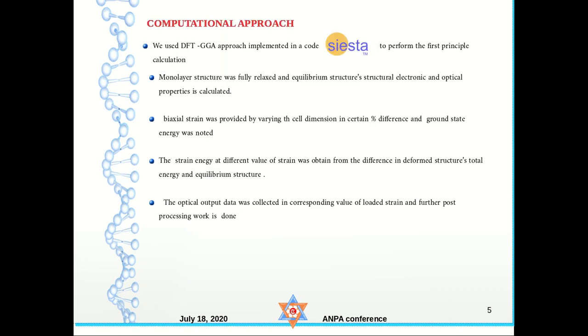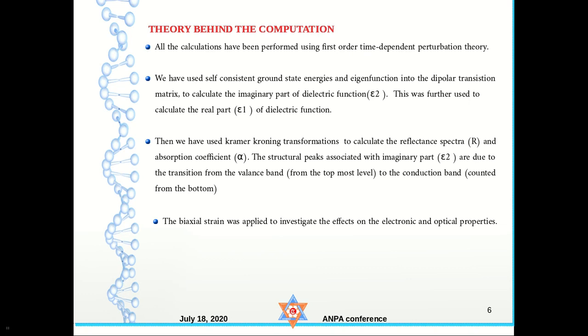We use the DFT-GGA approach implemented in the SIESTA code. First we design and model the structure, then relax it to find the equilibrium structure. We investigate the electronic and optical properties, and then apply biaxial strain within the elastic limit using both tensile and compressive strain to study these optical and electronic properties.